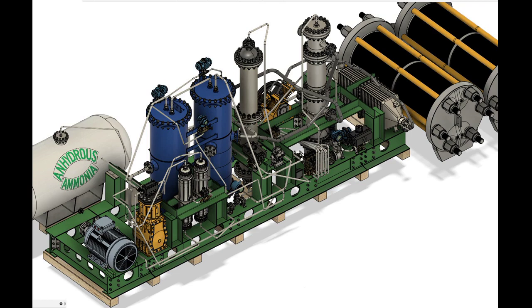The approximate size of a 13-liter reactor vessel is 300 mm wide and 1,400 mm tall. This is for a reactor that is capable of producing 1.26 tons of ammonia per day, at Wustite catalyst activity levels at 200 bar. When the reactor is wrapped in microporous insulation, an additional 10 centimeters of diameter would be added. The cost at volume for the converter should converge to below $5,000 if stainless steel is used, and around $10,000 for Inconel. In the current industry standard, a 600-ton per day plant is considered small.